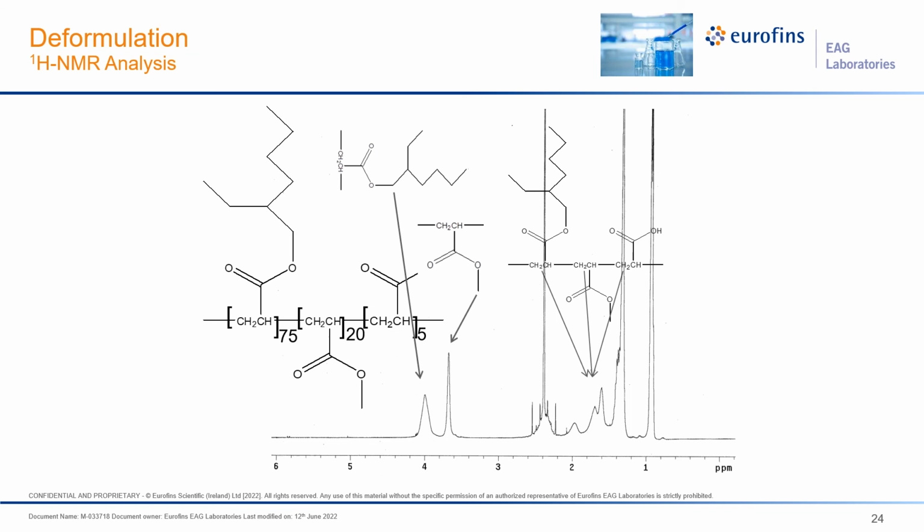In the spectrum in front of you, you can clearly see that the interfering solvent was indeed removed with our solvent extraction process. This allowed a much clearer picture of the sample peaks. Based on the structure identified by pyrolysis GCMS, we were able to further identify and quantitate the amount of the acrylate polymer present. That is seen by the fact that X became 75, Y became 20, and Z became 5. All these techniques were pulled together and yielded this information.